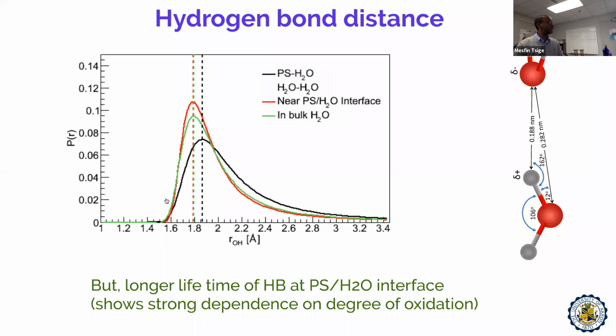It shows the usual Gaussian behavior. And then when we look at near the surface, we see a similar Gaussian behavior. The location doesn't change much. The peak, it peaks around the same value. So we didn't observe much change. There could be slight changes, in how much the value would differ at higher ROH distance.